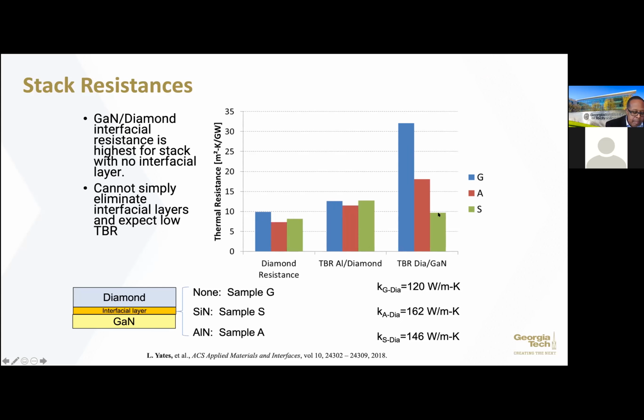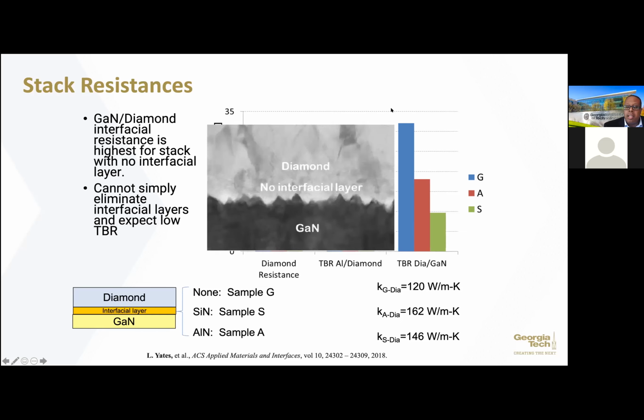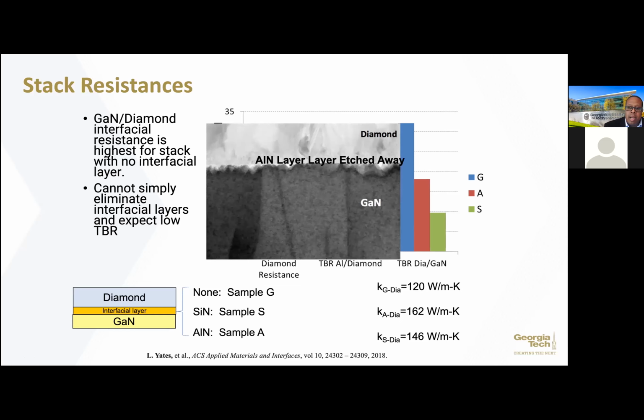So what's happening? If I try to get rid of that thermal interface altogether, based on just handbook calculations, you would say that the thermal resistance should go down, but it's actually going up. Well, the hydrogen that's in the plasma from the diamond growth actually begins to eat the gallium nitride, and so you introduce defects. And so this is why you have to have some sort of interfacial layer there when you're trying to grow directly. When we do aluminum nitride, we've seen some areas for this particular one that's been etched, that's been removed. And so you get some unevenness there. So we think that's where that thermal resistance is coming from.